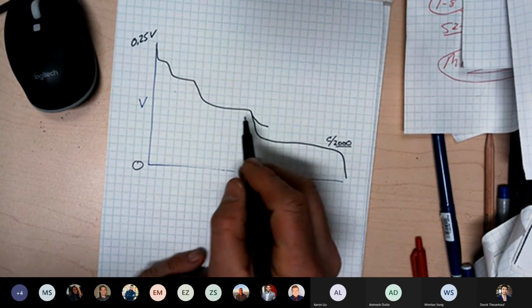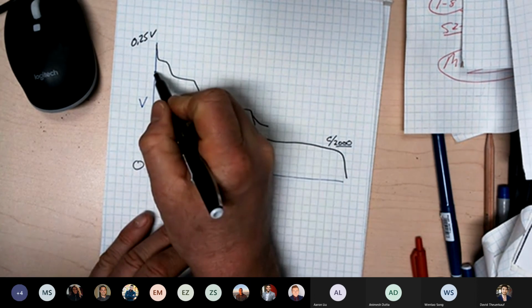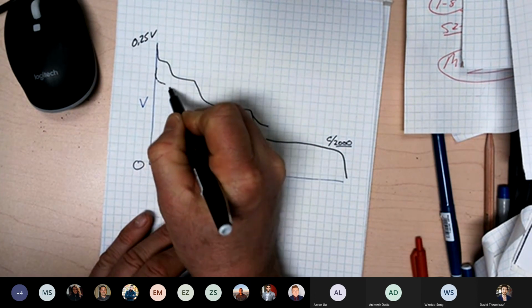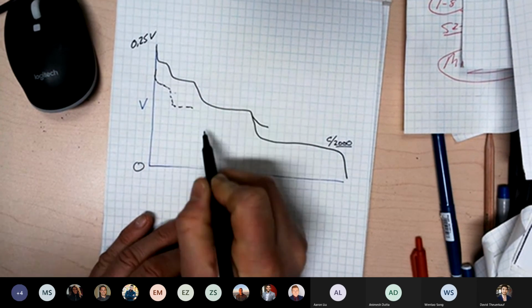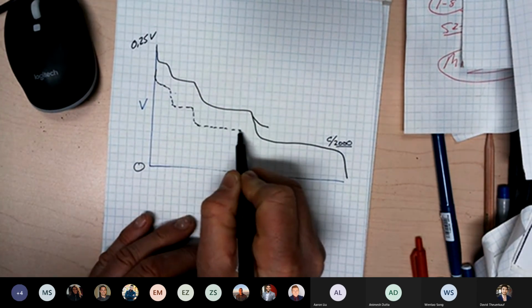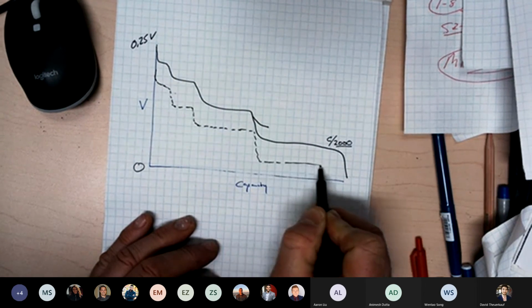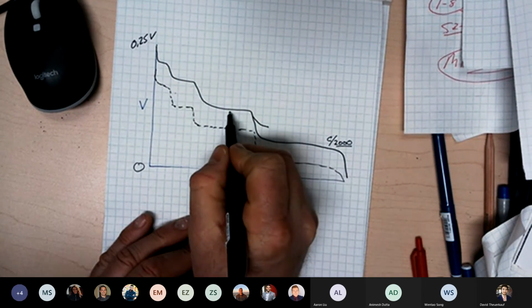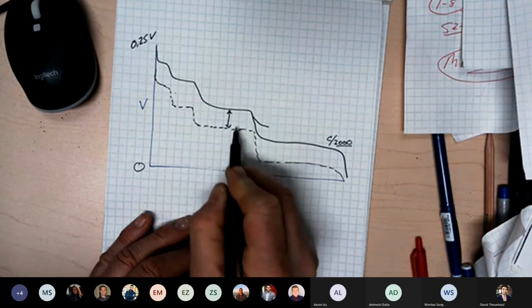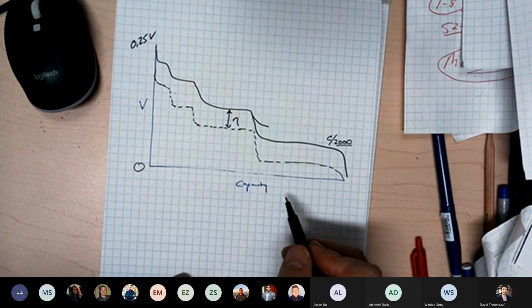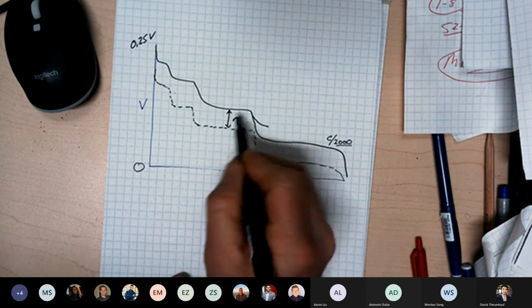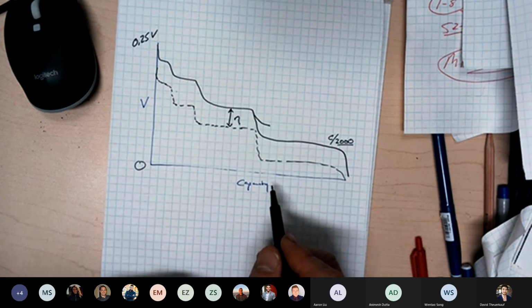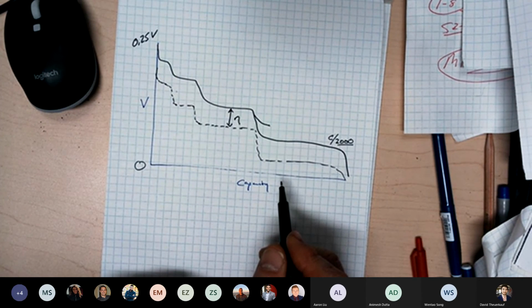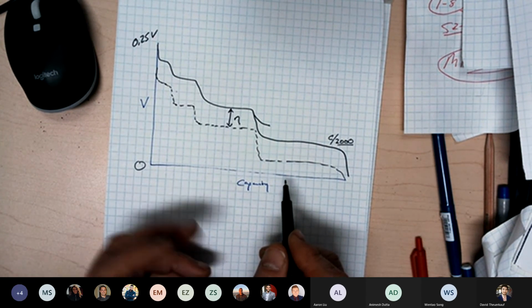But anyway. Okay, so then you start running at higher rate. And what you'll find out is this curve is shifted down. And in our laboratory, we call this delta V. This is half of delta V because we're only talking about the discharge direction. Okay, and that shift down, that's called the overvoltage. And it comes about from several factors: solid state diffusion in the graphite particles and the concentration change in the electrolyte from one part of the electrolyte to the other. We're going to come to both of these factors in this set of notes.